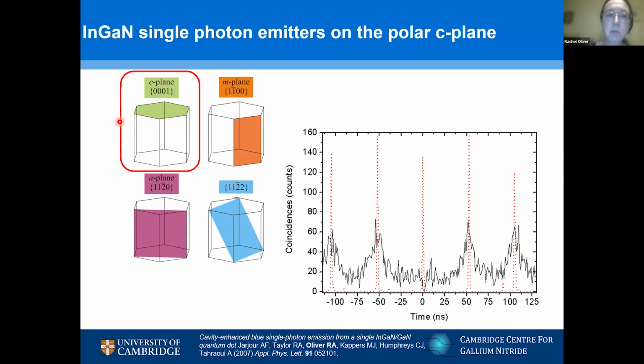Okay, so that was where we started with this common polar C-plane material. And we made the first indium gallium nitride single photon source in my lab in Cambridge. You can see here a black trace, which is our Hanbury Brown and Twiss trace for that first device. It's quite noisy. The device was not as bright as we might have liked, and our experiment wasn't as sensitive as we might have liked.